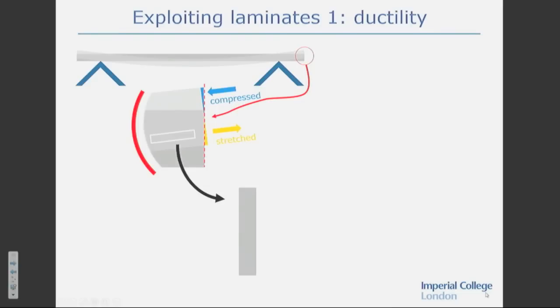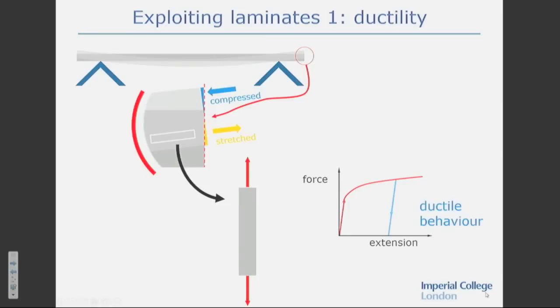If we cut some material out of the bottom part of the beam and took it away to the lab and did a tension test and looked at the force extension response, we would see it looked like this. And if we were only putting loads in here, we could load it and unload it and go back to the original shape. As soon as you get past this point where the material starts to yield, you're starting to lose stiffness, so for additional increments in force, you get larger and larger displacements. And if we unload it from part way along here before it finally comes apart, then we end up with a permanent displacement. And so this is called a ductile behavior.